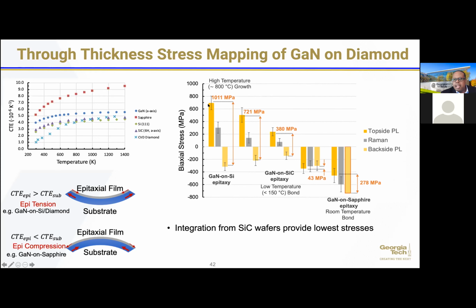So this is the growth. And so I get very, very high tensile stresses near the top surface. It can go compressive. There's a lot of work on, again, dialing this in to reduce these stress gradients. As I grow GaN on top of silicon epitaxy, I use that to then grow the diamond on the backside. So that was that carrier wafer, removing it from silicon, growing the diamond on the backside. This is what you're seeing, these large stresses here in these devices. If I grow GaN on silicon carbide, and now I do a low temperature bond, you see the stress gradients are much smaller. Now, if I do the plasma activated bonding that I showed you earlier with that silicon interlayer, what you see is that the stress gradients are really small, but now I flipped it to being compressive.